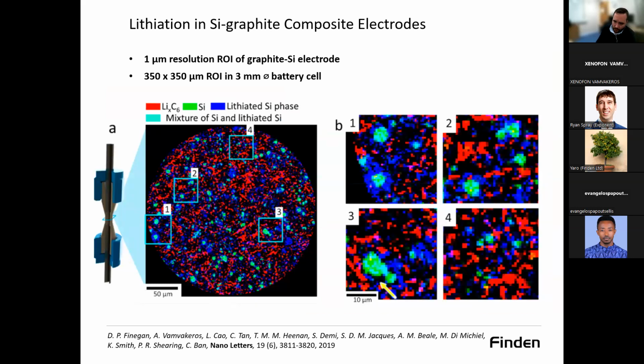ever performed. But before we go to the large batteries, we can have a look at this smaller scale, because industry is also often interested in studying the material properties. In this case, it was a small Swagelok cell, and we demonstrated the first region of interest XRD-CT. You can see that the diameter of the cell was about 3 millimeters, but we managed to reconstruct a very small region that was 350 microns with very high resolution and without any artifacts in these images. And this was a silicon graphite composite, and we were able to see the crystalline silicon particles, and we could see that at the periphery, there were amorphous